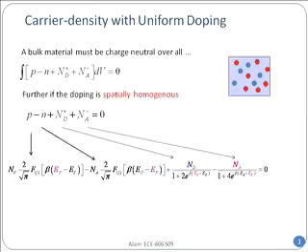Now, this is something I discussed in the previous lecture: in any semiconductor, let's say silicon, if I dope it with a certain amount of boron, which is a p-type dopant, an acceptor, and a certain number of donors, like phosphorus, then I will have a change of carrier concentration from the intrinsic value. The intrinsic value is very small, right? 10 to the power 10 in silicon, out of 10 to the power 22 atoms.